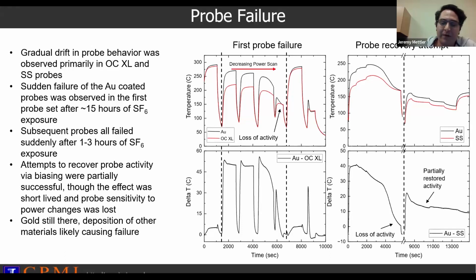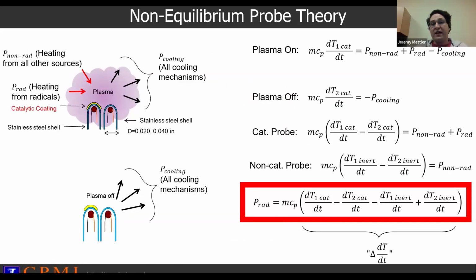So that, coupled with the issues we saw in getting agreement between the radical probe and the spectroscopic measurements, led us to reconsider a few things. And so the first one was, in all the previous examples I've shown you, we evaluate these radical probes at thermal equilibrium. So we let the temperature run out until both the reactive probe and the non-reactive probe have reached a steady state of sorts. And this is fine in probes that have a long lifetime. You could run some long scans and measure each condition, but since the lifetime of the gold seemed to be quite limited, we wanted to try to optimize how many measurements we could take for a given probe. And so we looked at ways to analyze the probes off equilibrium.